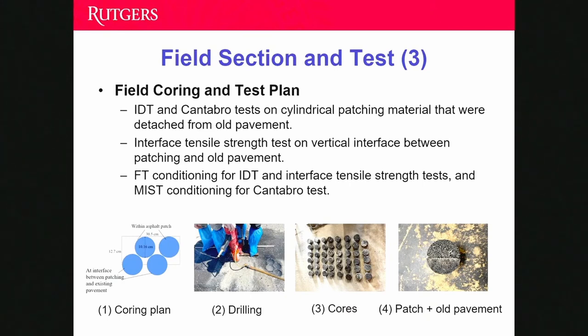And based on the previous lab testing, we found that the freeze-thaw conditioning is more critical for IDT and interface condition, and the mist conditioning is more critical for the abrasion resistance. So similarly, in the mechanical testing of the field cores, we applied the freeze-thaw conditioning for IDT and the interface, and applied mist conditioning for the Cantabro test.